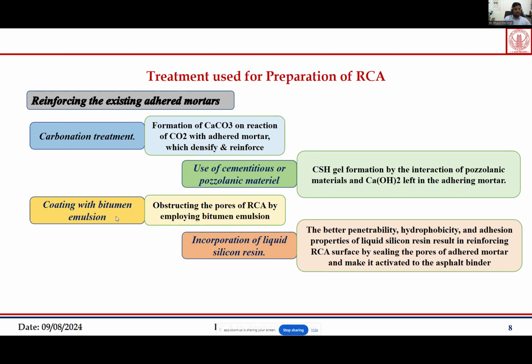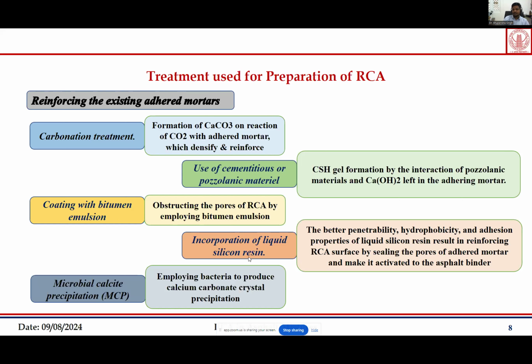Then specifically when we are using these aggregates for asphalt mixture purposes, we coat these aggregates with bitumen emulsion also. Because of this emulsion, it obstructs the pores of RCA, and it improves the bond between adhered mortar and those aggregates. So that solves our problem with the detachment of this adhered mortar in the mix, and it also reduces your water absorption, because pores get clogged up.